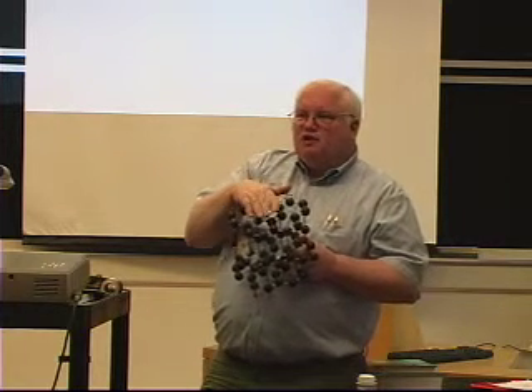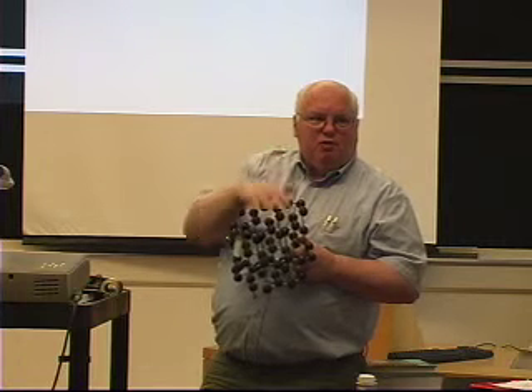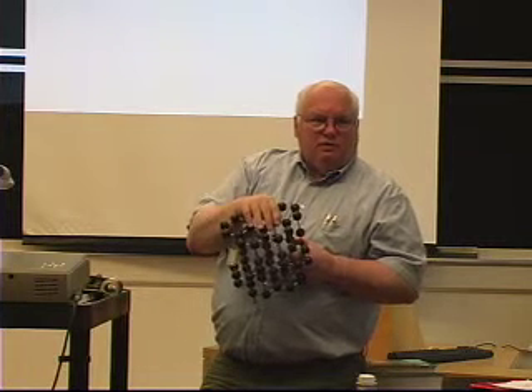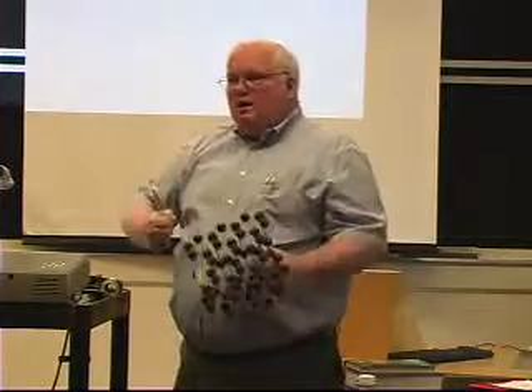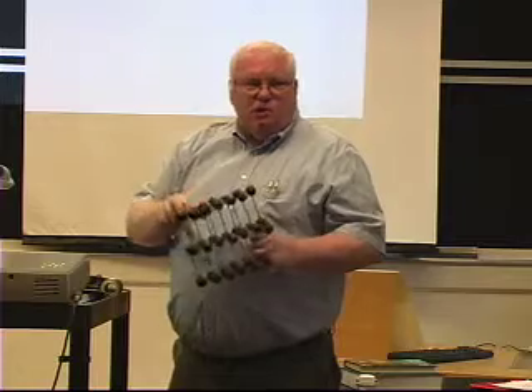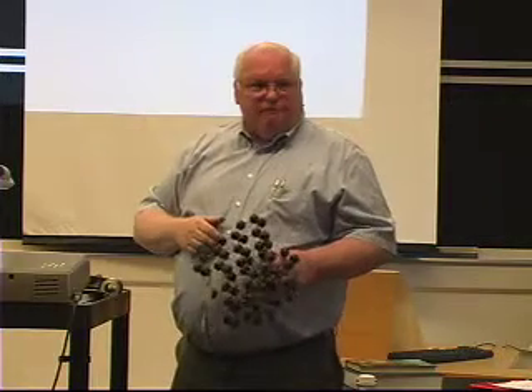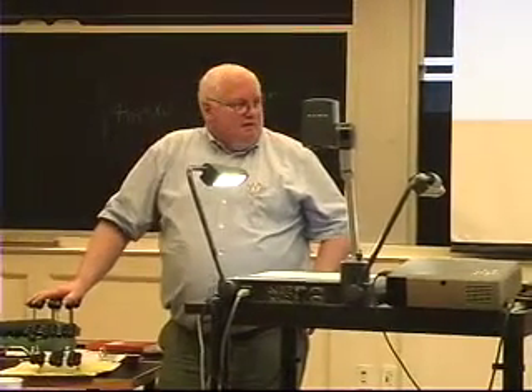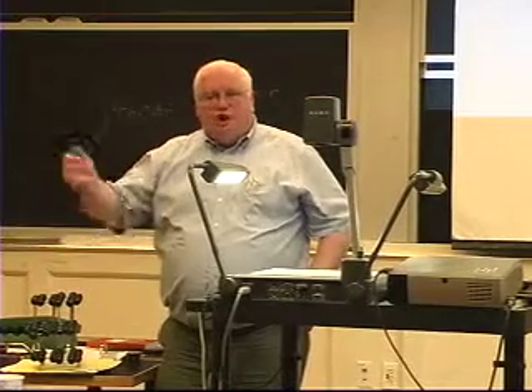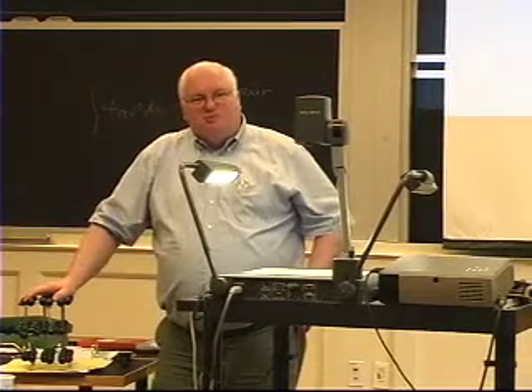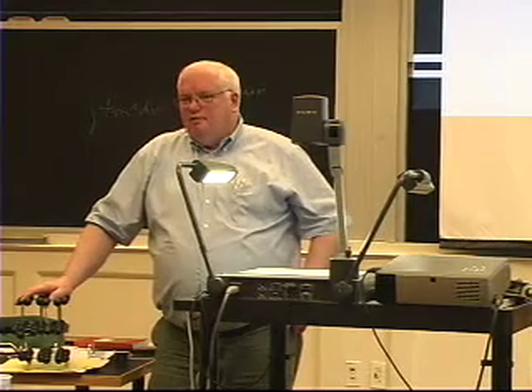The surface energy of a carbon-oxygen surface is very low compared to a pure carbon surface. The excess energy, that carbon surface wants to find something that it can grab onto and lower its energy, and oxygen is the perfect thing, except if you've got a vacuum, you can pull it off. And that's exactly what happened. They found that in the vacuum of space, they basically turned their graphite lubricant into an abrasive, and they were having a few problems with some of the knobs and stuff. Okay, wasn't good. The astronauts were not happy.